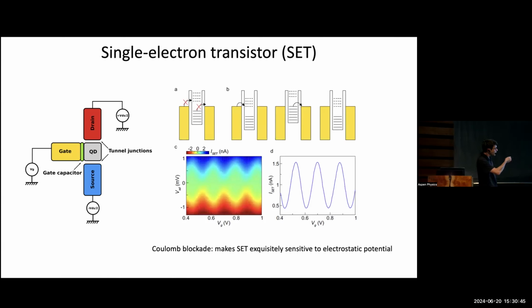Well, as long as you make this quantum dot small enough, adding additional charges to it costs some large charging energy. There's some Coulomb repulsion with all the electrons that are already occupying this metal island. And what that means is that there's an energy gap between the highest occupied state of the island and the lowest unoccupied state. It's given by e squared over 2C. And if the Fermi level of your leads is aligned such that it's in this energy gap, and if your temperature is low enough, electrons can't hop from the source onto the island, they can't hop from the island onto the drain, and so you get no conduction.